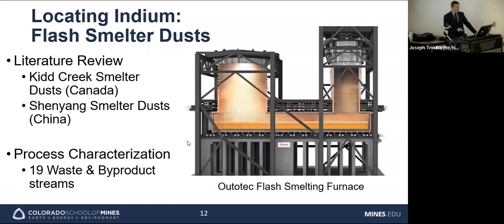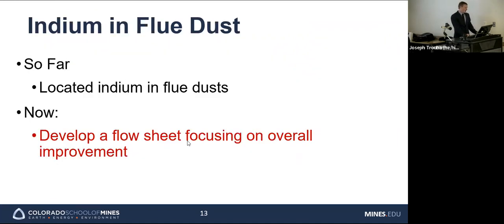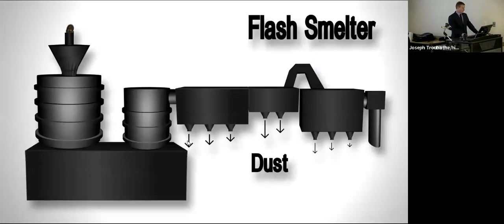Peru? So you'll see here, we're looking for indium in a copper deposit, and there's two sources in literature. There's the Kidd Creek smelter and the Shenyang smelter in China, and they're both copper zinc deposits. So it's interesting that you say that. In addition to looking at the flue dust, however, we characterized 19 different streams throughout the process to identify how indium flows. Here you see a flash smelter, like the one used at Rio Tinto Kennecott. The concentrate comes in here and then leaves through the dust. After our survey, we did find indium concentrated within flue dusts.